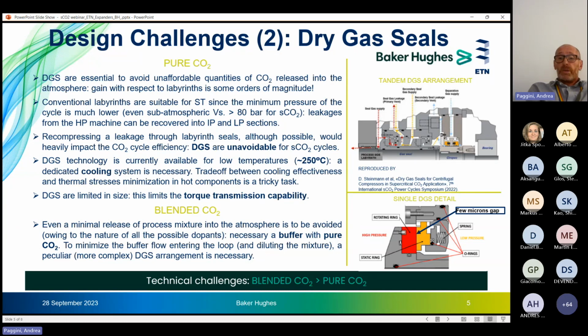And if you wish to minimize the amount of pure CO2 buffer flow, since it cannot be avoided, it enters the process loop, contributing to a certain dilution of the working mixtures. All these requirements force a peculiar dry gas seal design in a component which has already its own criticalities. So from the dry gas seal standpoint, we could say that blended CO2 expanders are a bit more critical than expanders for pure CO2.